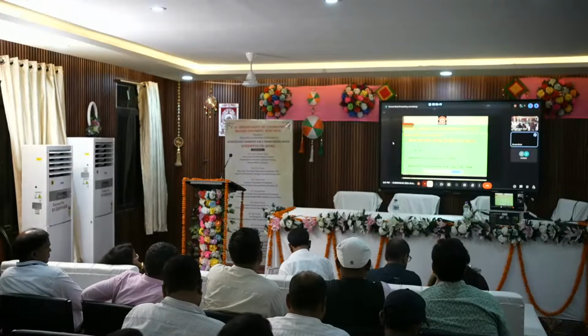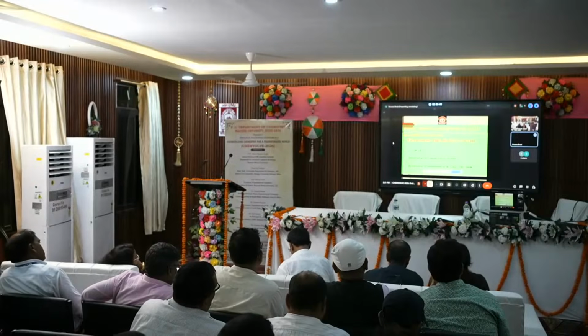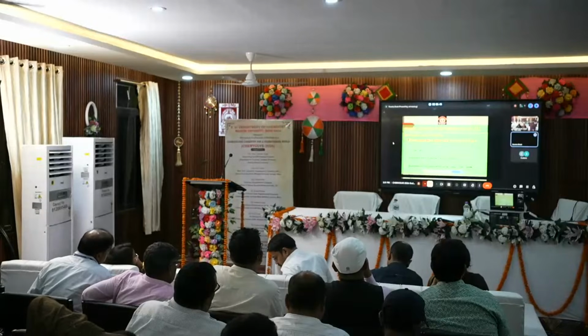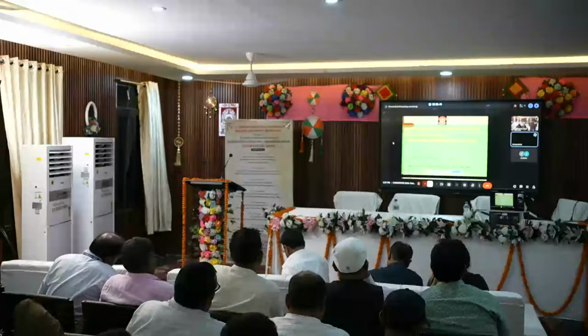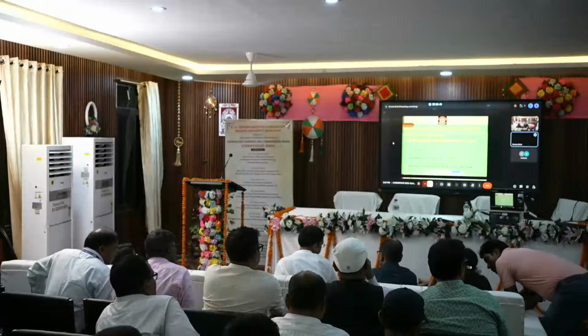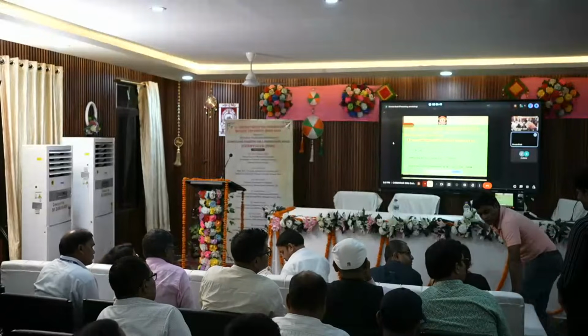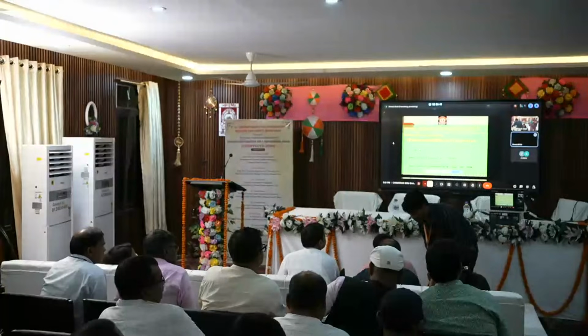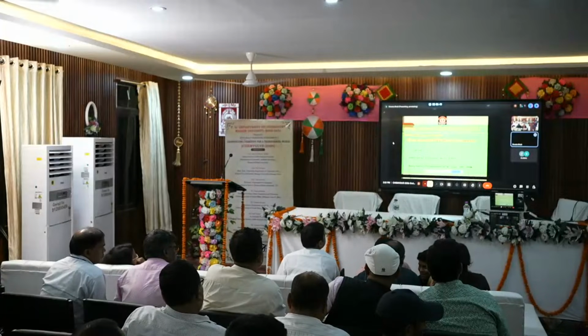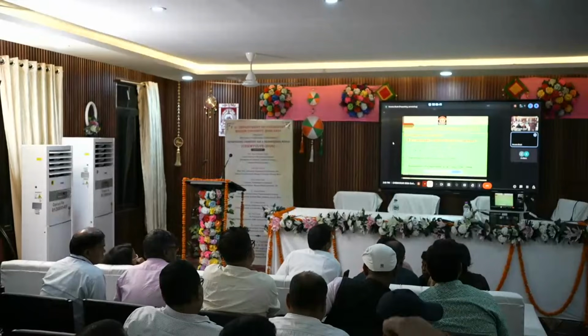So what are the factors on which we have to focus on this issue? In the last slide we saw that an ideal capacitor material should have a dielectric constant of more than 10,000, which will be a much better material. CCTO has a dielectric constant of more than 10,000. It means it will be a better capacitor material for futuristic devices. It has also been seen that this material is independent of frequency up to 10 megahertz. It is also thermally stable, which means there is no phase transition between 100 and 600 Kelvin. So this material is far better than the commercial material barium titanate that we are now using.